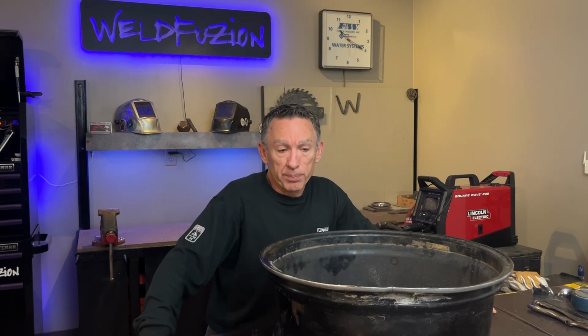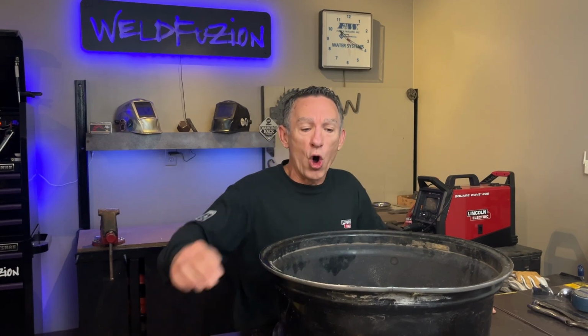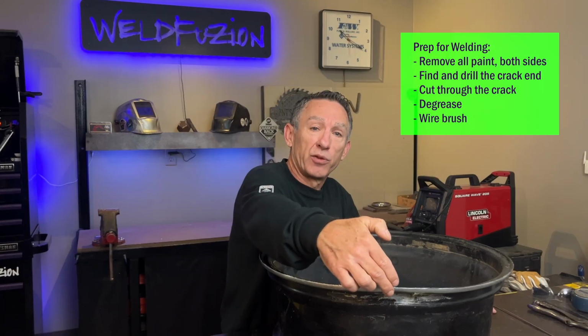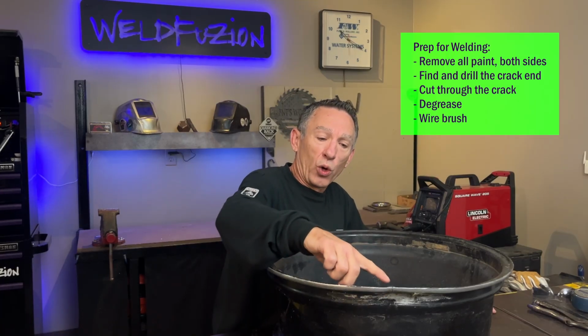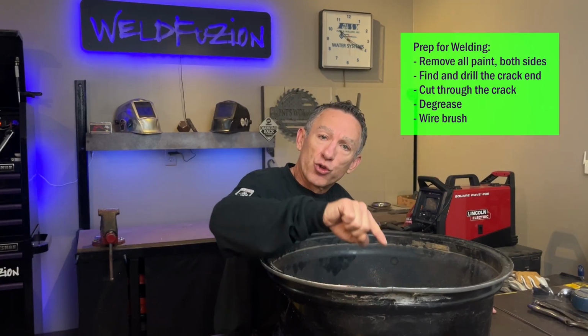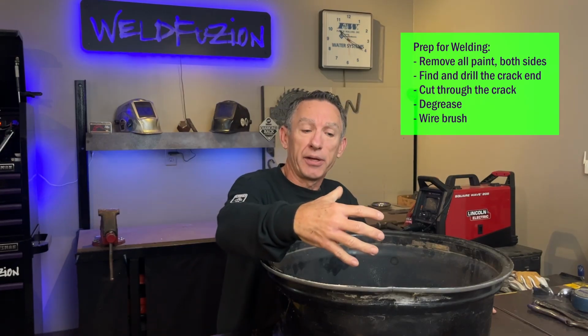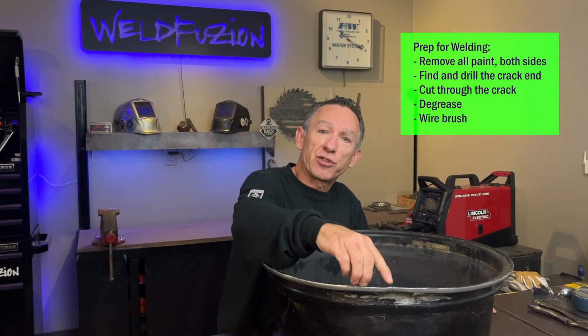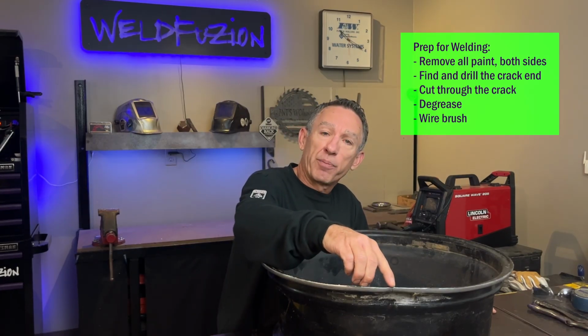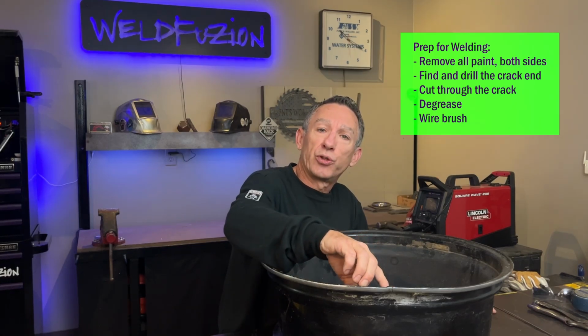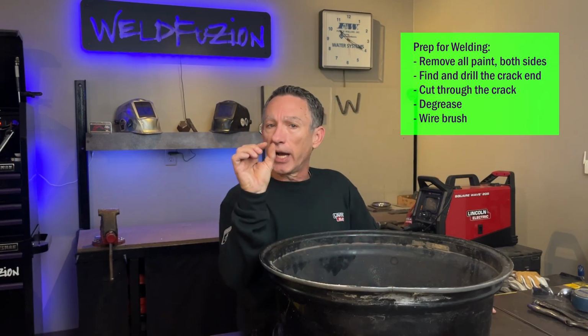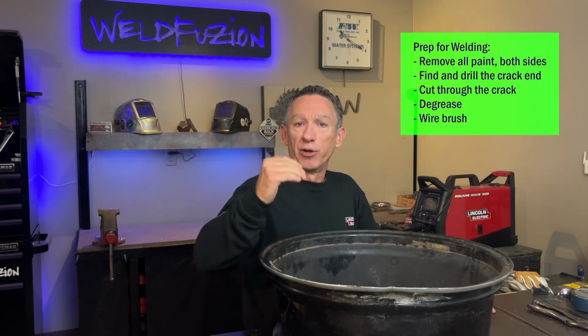In addition, as we prep this thing, we're going to remove all the paint on both sides of the wheel here. And then we're going to find the end of the crack. We're going to drill a hole in it so it can't propagate. And then we're going to go ahead and chase this crack right down from the outside of the edge of the rim here all the way through to the hole that we drilled, so that we've got a nice thin slice to fill back in completely with filler metal.